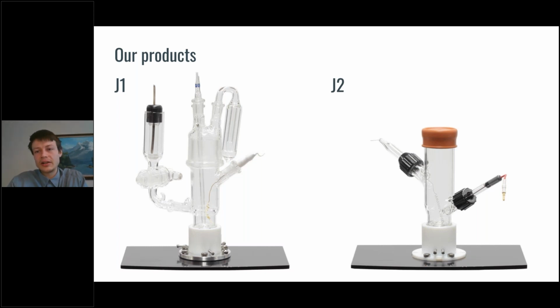So you have your counter electrode and your reference electrode and your working electrode. And the novel contribution that we recently made was to improve the electrical contact made onto your working electrode with a spring-loaded pin design, which delicately makes contact with the film so that you do not damage your metal film, which can often be very delicate and prone to damage.